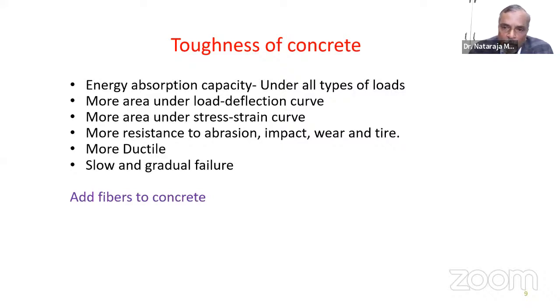More resistance to abrasion, impact, wear and tear is mainly because of the addition of different types of fiber. But if you add steel fiber, there is a lot of improvement in these properties, mainly from the point of strength and of course from the point of energy absorption capability. And that is where structurally your concrete becomes better and better with the addition of steel fiber. So what I want to tell you is that with this addition of fiber, your concrete will become more ductile. Obviously, the failure of the concrete will be rather slow and gradual. So it is not an instantaneous type of failure. It is not a catastrophic type of failure. So that is where you should be very, very happy to have these steel fibers introduced into the concrete. Obviously, add fibers to concrete so that many of the performance characteristics of your pavement increase.